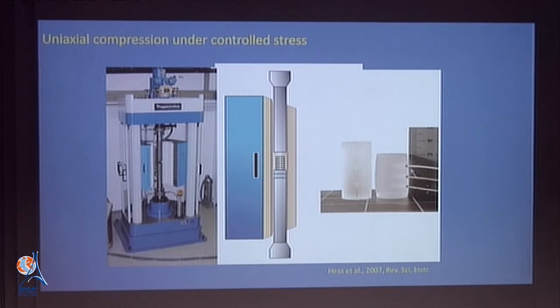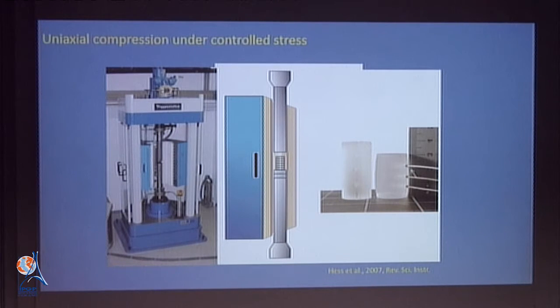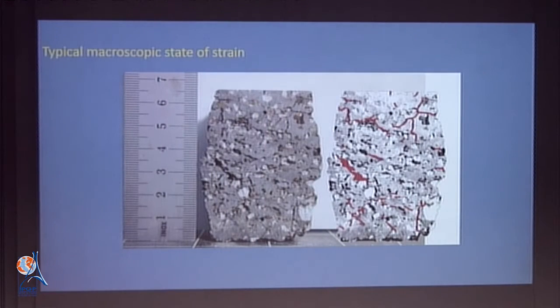What you see here is a big uniaxial press. On the right-hand side, you see before and after samples of a standard material. You see 3 big steel pieces going into one of those samples. Those are sheathed thermocouples, and we literally compress that cylinder from its original height down to this slightly barreled shorter height, and in doing so, we measure the temperature increase. Here we've done it with the dome lava.